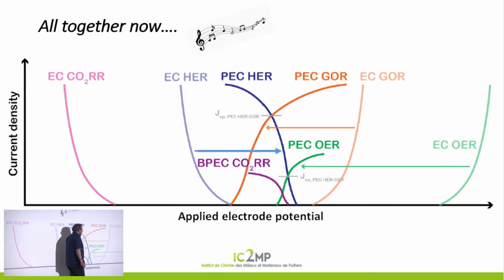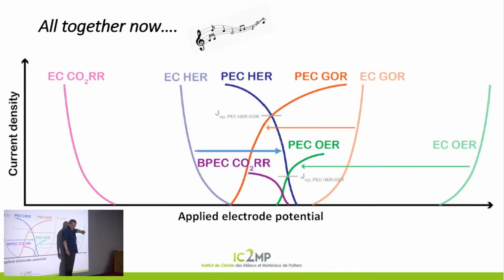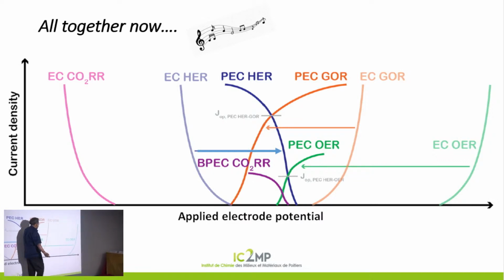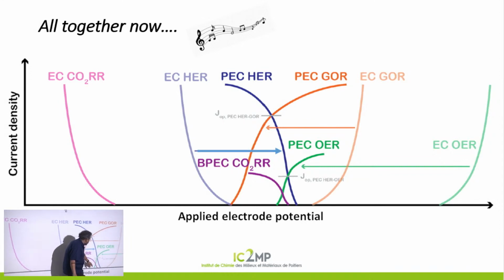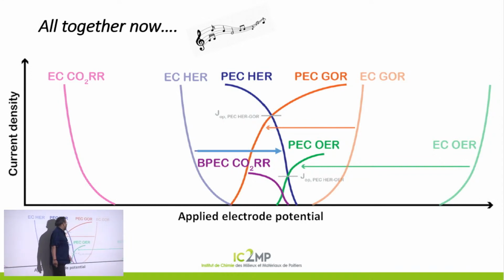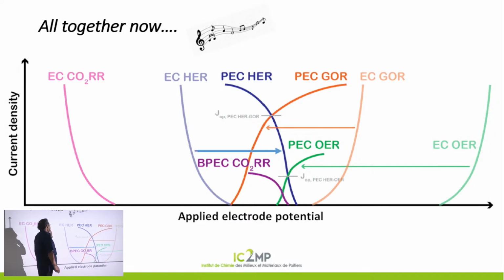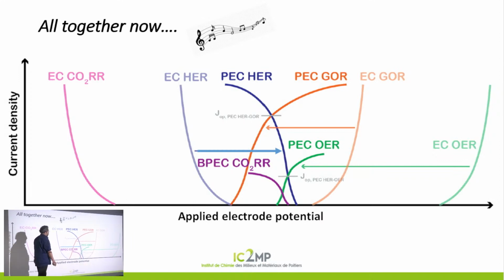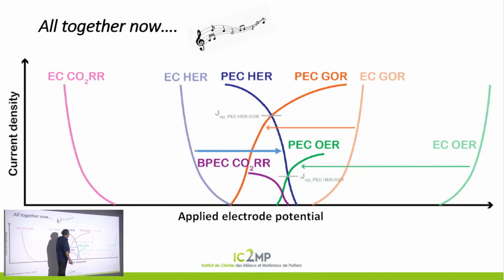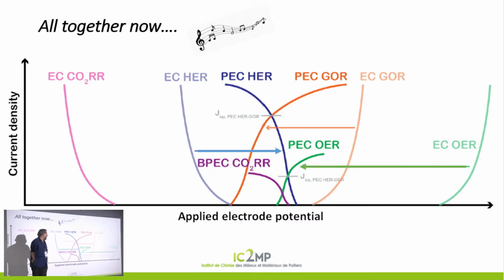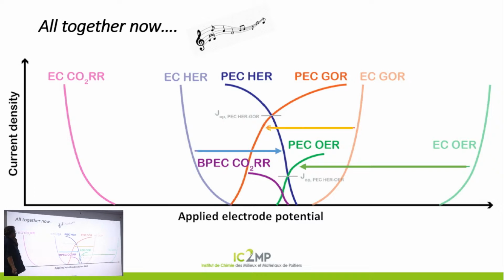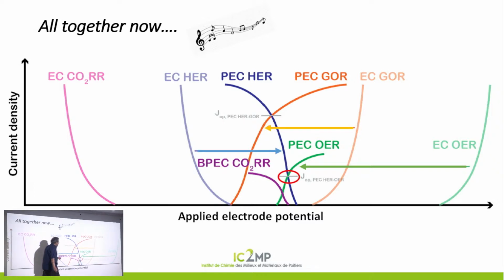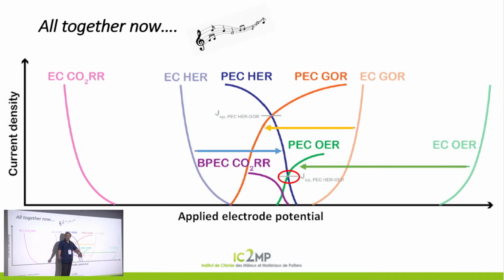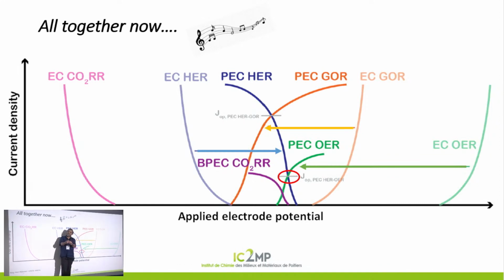Okay, I hope so. I saw very quickly that the oxygen evolution reaction takes place here, at a very high potential, okay? And when you use a semiconductor, then you can observe that the oxygen evolution reaction takes place here. So now what we need is to have a material able to evolve hydrogen. Let's say this is this process here, okay? And then what is important to take care of now is that we want to develop a system able to increase the operational current here, okay? And one way to increase this operational current, that means that the system put together could work alone, not to fix a potential.